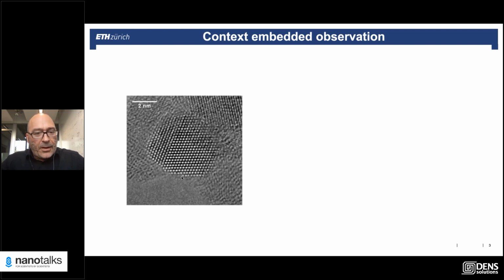And when you look at this particle, trying to understand how the catalyst works, you look at the surface atoms and you see some of these atoms at steps are slightly under-coordinated. And you could imagine that these are sites where a catalytic reaction could happen. Now, there are two problems here. The first problem is that although we have all these details, it's not a representative state, because a catalyst is normally not in vacuum. It's surrounded by gases, at some kind of temperature and gas condition.